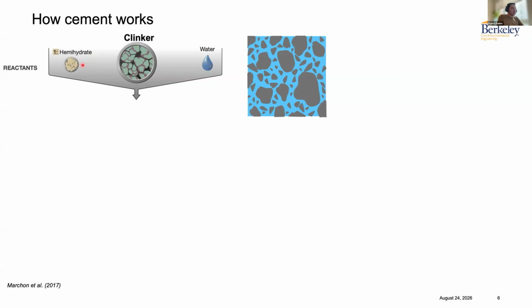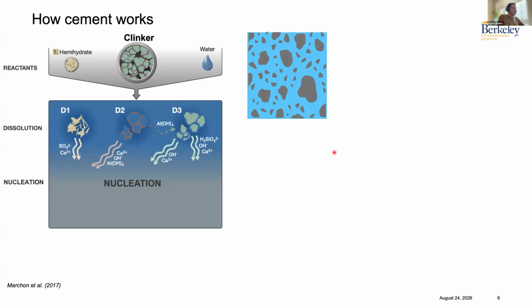We combine that with a little bit of a sulfate carrier and water. These grains of cement are going to dissolve, and this dissolution is going to put ionic species in the water, which is not going to be water anymore. This is a solution that we call the pore solution.